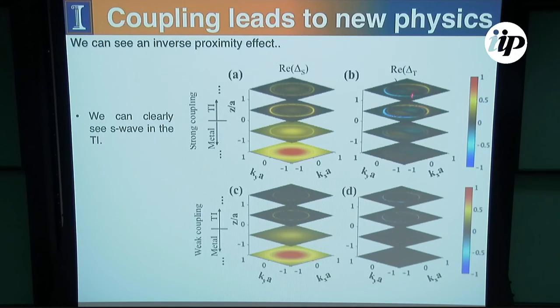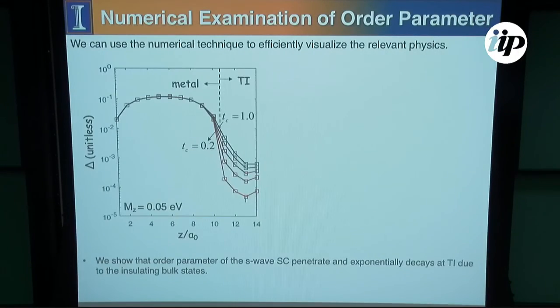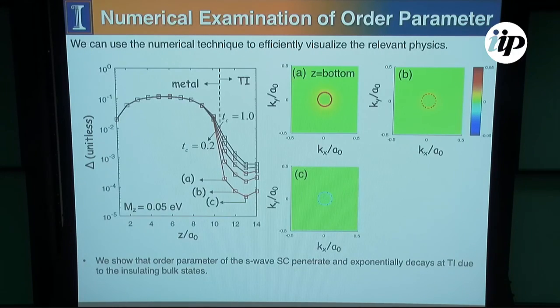So this is superconductor up here, and this is TI here, and this is superconductor. So you can see there's some signal here, but there's no signal here. So we wanted to visualize the relevant physics, so we can confirm that we actually have a switching from symmetric to antisymmetric by looking at different points. So this is, of course, the superconducting order parameters. So this is both S and P. The chemical potential here is not in the bands, sorry, it's in the surface states. So this is why we only see the surface state contribution here.